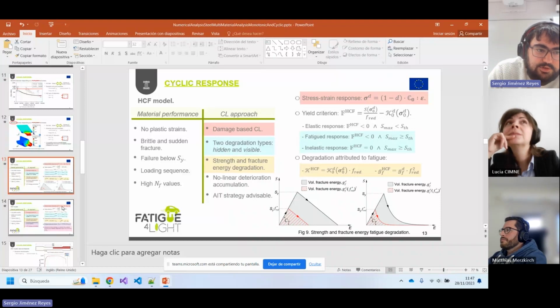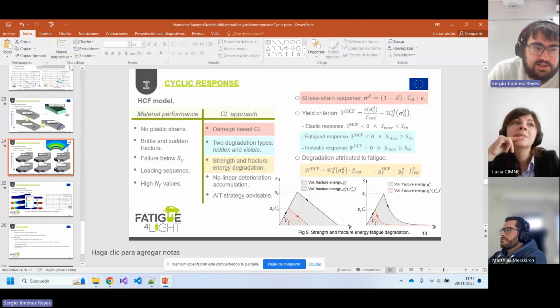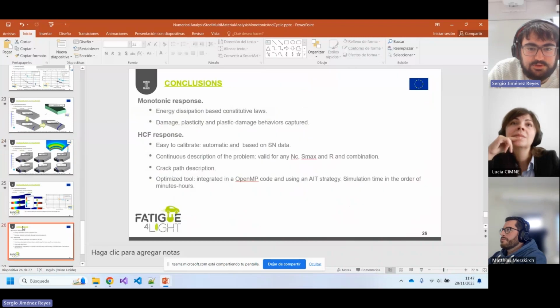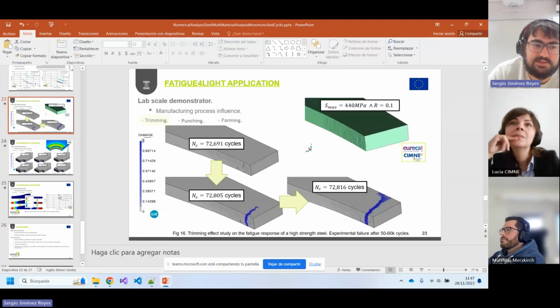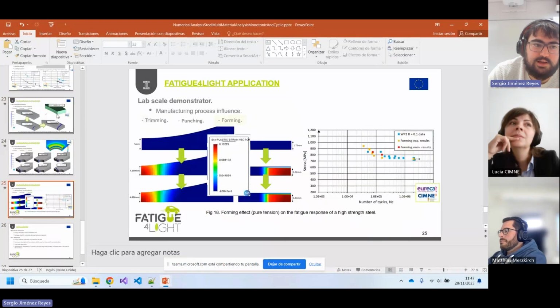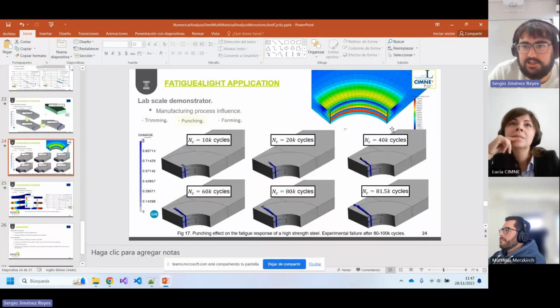In the simulations that I present here, as I was commenting in the conclusions section, the time is between minutes and hours, depending on the case study. In these ones, it took only minutes to run. But in this case, considering the residual stress information, it took hours because we identified non-linearities since